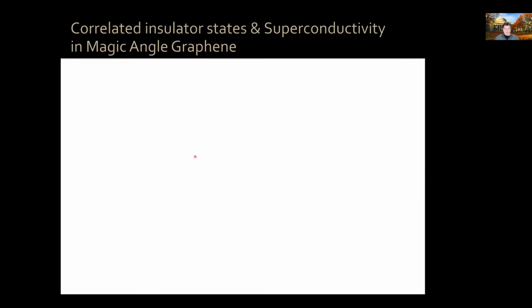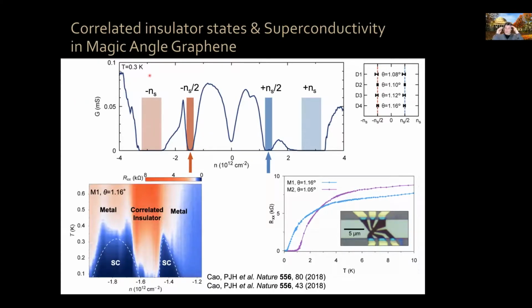Now, what my group discovered back in 2018 is that if you make magic angle twisted bilayer graphene devices and you position your Fermi level, your chemical potential, in these flat bands, you can find an unusual set of correlated insulator states, which are due to strong electron-electron interactions. And then if you dope a little bit away with charge carriers from that point, you have actually electrically tunable superconductivity. So magic angle twisted bilayer graphene superconducts. This was the first time that a purely carbon system, which was just electrostatically doped, became a superconductor.